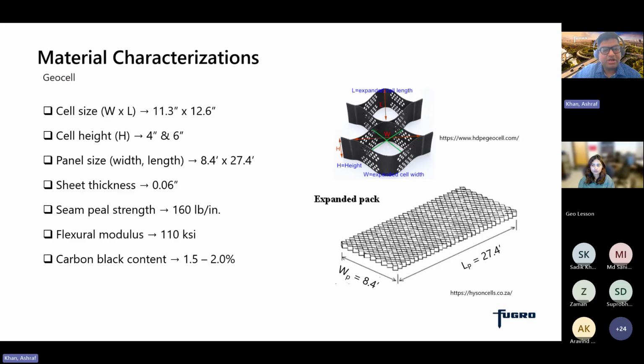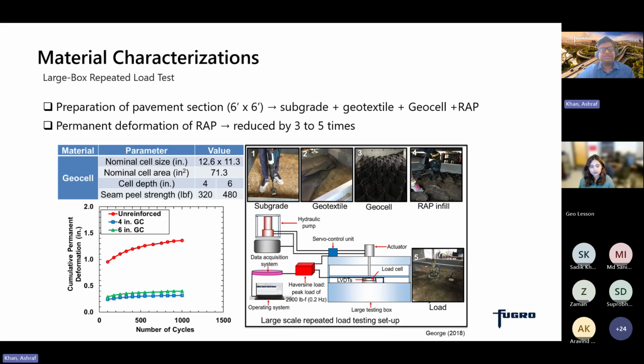With that, let's talk about some laboratory studies with Geocells. To simulate the pavement loading on Geocell reinforced wrap base layer, we constructed a test section, which is like 6 feet by 6 feet box. And you can see the bottom of the box, we had subgrade, which is 2 feet thick. Then we used geotextile for separation. On top of that, we had Geocell, which was filled with recycled asphalt pavement from the same source.